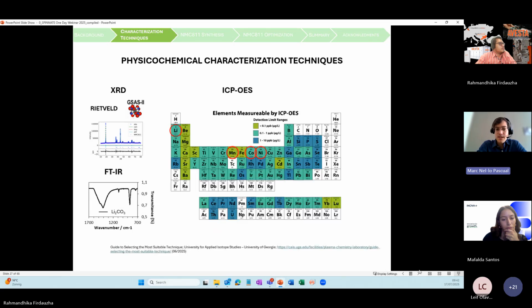And the last technique I want to mention to characterize these materials is ICP. ICP is a very powerful technique in order to measure the concentration of your elements. Usually, most studies only study the lithium concentration because it's an element that when you calcine at high temperature, you're expecting it to evaporate.